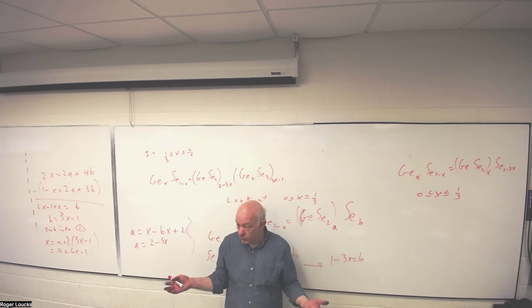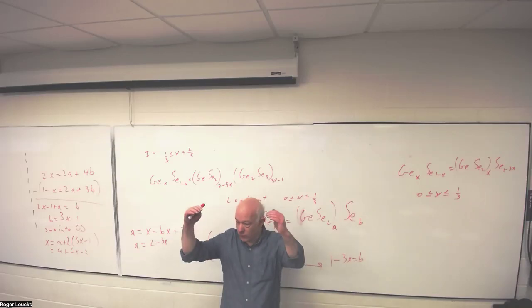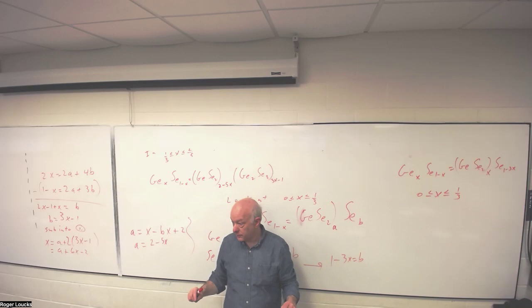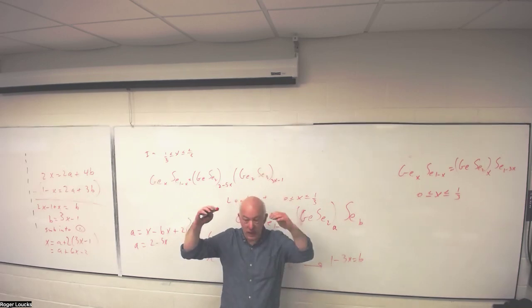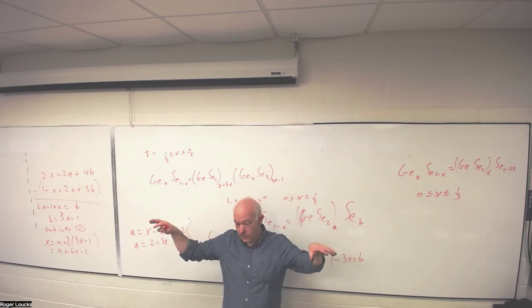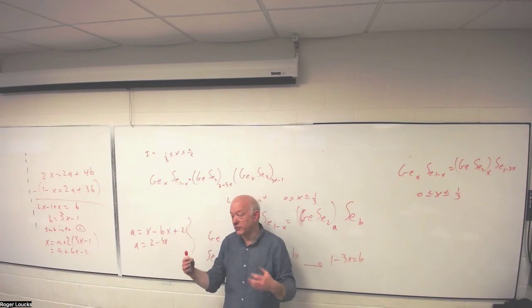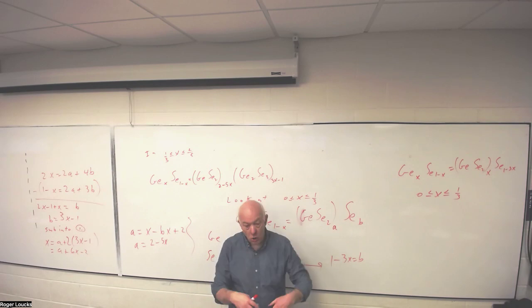Now, maybe some of these are important, maybe they're not. We don't know. But what we're going to do is say that as we lower the temperature, certain ones of those bonds are going to come in at a certain time. So we're going to start off with a high temperature. At a high temperature, how many constraints do we have? None. We're going to start lowering the temperature, and then what happens? Either the linear bonds come in or the angular bonds come in, probably the angular being the first.